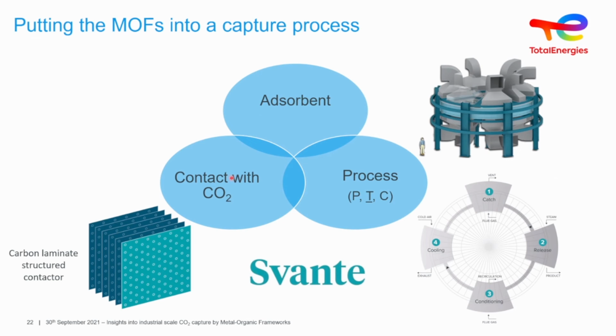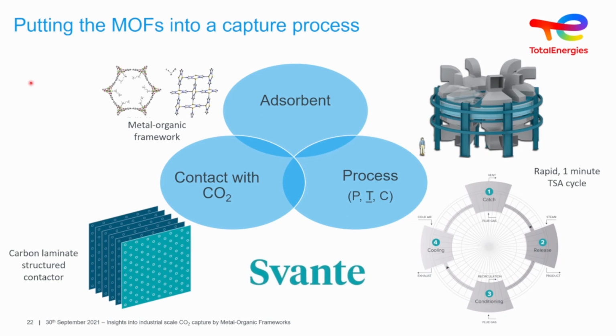So the adsorbent materials that they were looking at initially were amine functionalized silicas. But amine functionalized silicas don't give us this nice cycle. There are one or two problems with these amine functionalized silicas. But there are metal organic frameworks that they've been looking at. You can see this functionalized MOF74 type structure. This is one of them, but this material here is called CALF-20. You can see it's a very, very simple material developed by George Shimizu. And this material is making a difference and is being tested at the moment on this large scale.